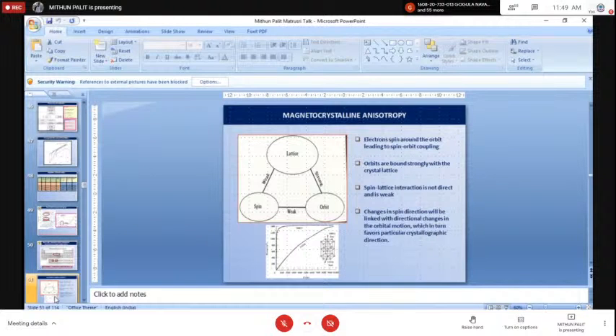Therefore, if you combine these two, but unfortunately, the magnetic order of this rare earth material is retained only at a lower temperature. At room temperature, most of them are merely paramagnetic. Transition metals on the other side have very high Curie temperature, and having very high Curie temperature, they are actually magnetic till much above room temperature.